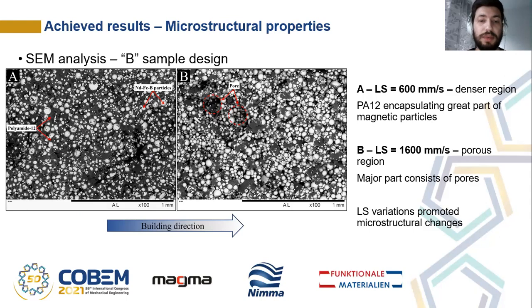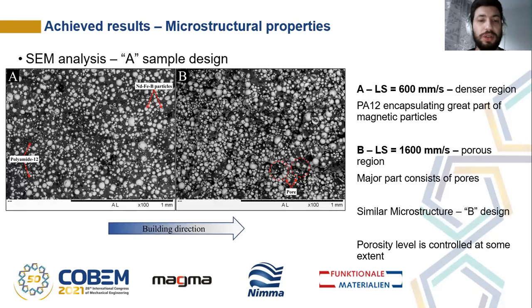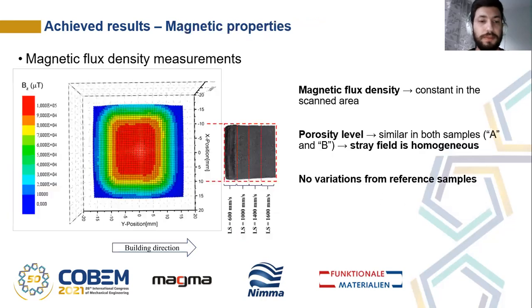In image B, from the same sample, this region is now majorly composed of pores. A similar microstructure is observed in the A sample. Figure A is from the region built with elevated energy density and B with the reduced energy density. SEM observations show that both approaches were effective to induce different porosity levels to some extent.